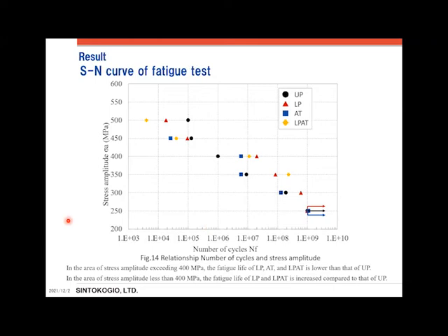The figure shows the relationship between stress amplitude and the number of cycles. The fatigue limit values of stress amplitude were the same for UP, LP, and AT. In the area of stress amplitude exceeding 400 megapascal, the fatigue life of LP, AT, and LP-AT is lower than that of UP. However, in the area of stress amplitude less than 400 megapascal, the fatigue life of LP and LP-AT is increased compared to that of UP.